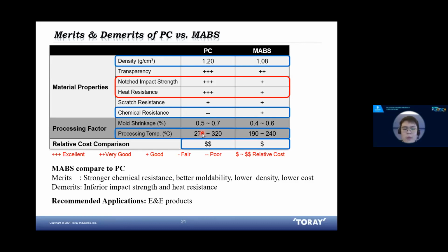However, on the PC side, one of the highlights we found is that the density of the MABS is lower than PC. So mainly this plays a role where a part can use less material compared to the PC. And then on the chemical resistance side, MABS is better than the PC. And in terms of processing temperature, MABS uses a lower temperature compared to the PC. So in other words, using a lower temperature also means energy saving compared to the PC grade.